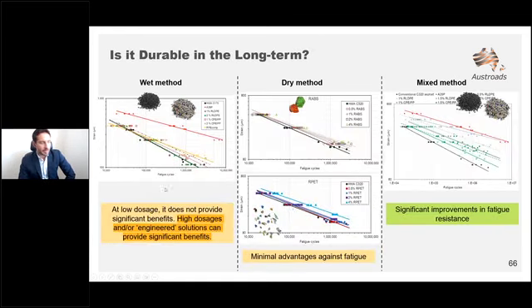So looking at the fatigue life, on the left-hand side, again, you have the wet methods, and you can appreciate there is quite a big difference between these colored lines at the bottom, which are essentially the representation of the standard conventional unmodified asphalt and the plastic modified asphalt mixes at low plastic content, all the way up to the red line, which is the A35P, so the conventional polymer modified asphalt. So at low dosages, it really does not provide any significant benefit in terms of fatigue. However, we can engineer the product and bring it up to higher levels of plastics to provide a little bit better fatigue resistance. It's very good for rutting. In terms of fatigue, you really need to engineer the product. You can maybe even think about mixing and blending different polymers, and one of them being recycled plastics.